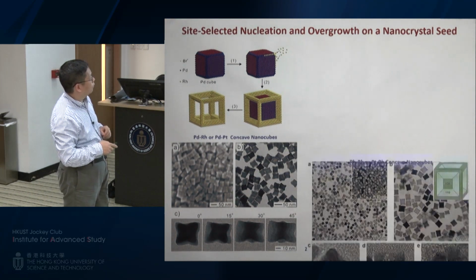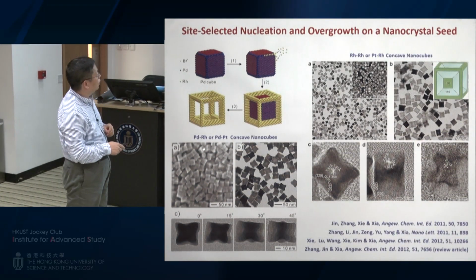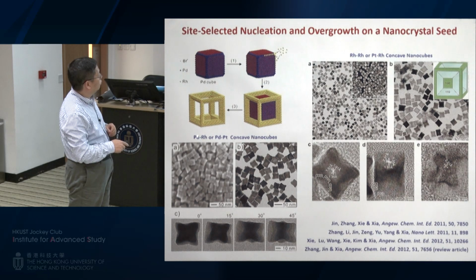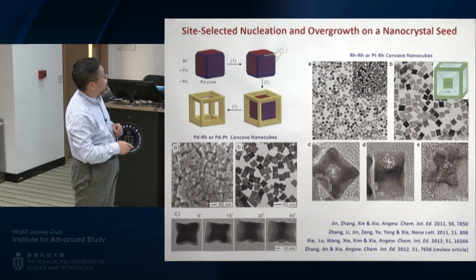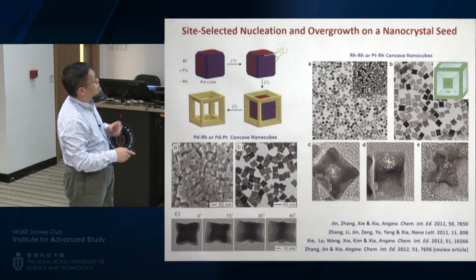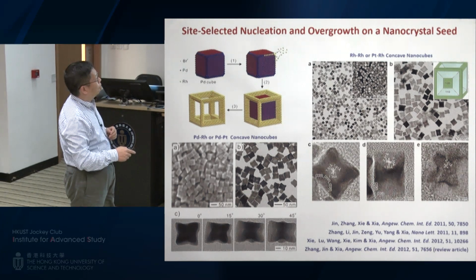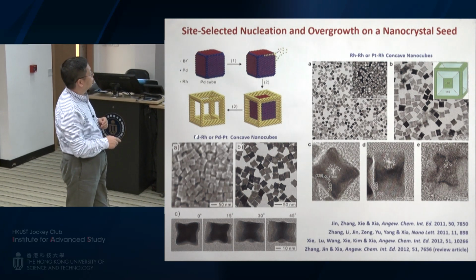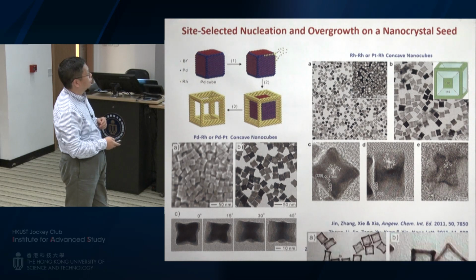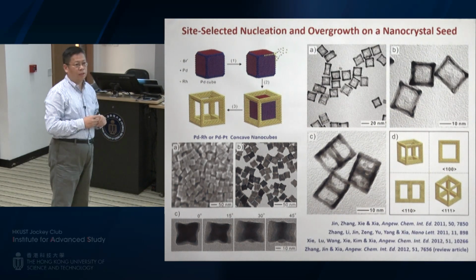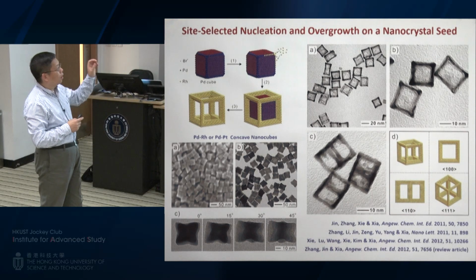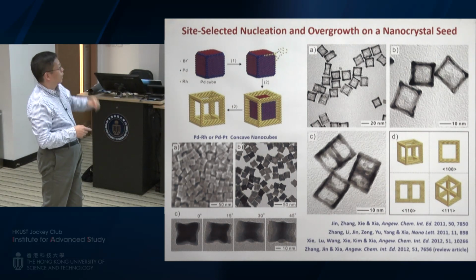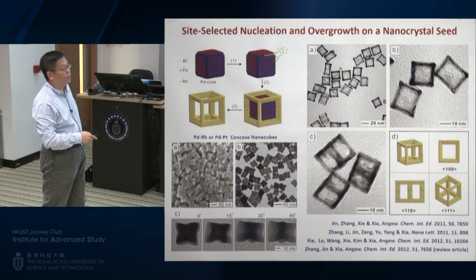And here I just show you some different combinations of metals we have tested. The first metal is in the core. The second metal is at the frame side. So you can have a palladium seed with rhodium grown on it, and a palladium seed with platinum grown on it. And this could even be the same metal, like rhodium, platinum, rhodium, and so on and so forth. For the palladium rhodium system, like this one, we can etch away the palladium very easily because rhodium is less reactive compared to palladium. So eventually you can make these nanoframe structures.